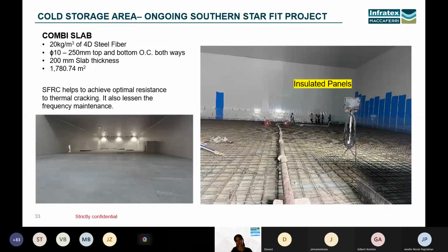They used a combination slab for their cold storage with a dosage of 20 kilograms per cubic meter of 4D steel fibers with 10 millimeter diameter rebars, 250 millimeter top and bottom on center both ways. So it has a slab thickness of 200 millimeters with a total area of 1,780.74 square meters.